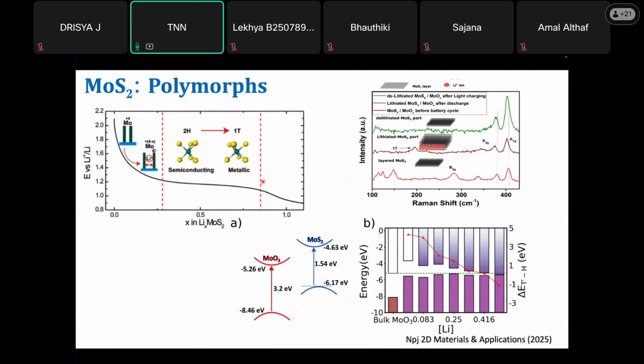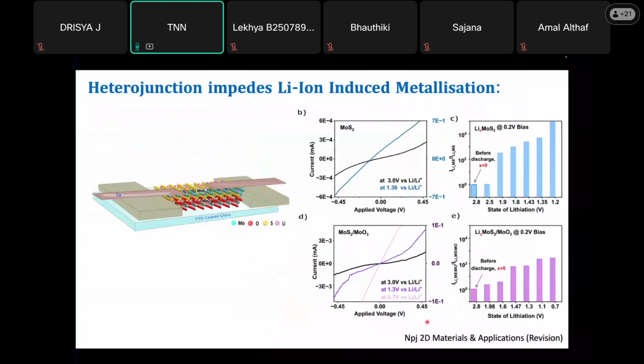So somebody from Cambridge, a very famous scientist, challenged this concept. This will not work. Then it was our duty to prove that this will work. There is fundamentally something else happening, and we found that yes, when you form a type 2 semiconductor heterostructure like this, MoS2 to MoO3, the phase transition can be delayed. It can hold almost double the amount of lithium it otherwise can hold before the metallization happens. This we have proven theoretically, and we have shown experimentally also. If you have an MoS2 to MoOx heterostructure and study the conductivity, the metallization happening in MoS2 is rather very slow, unlike in the case of pristine MoS2.